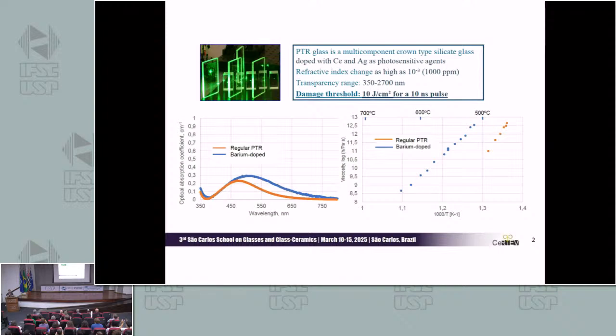First is irradiation, at which step the silver ions get an electron. At the second stage, it's a heat treatment. The silver atoms aggregate into nanocrystals, and at the third stage, at the heat treatment, the sodium fluoride aggregates on the silver nanoparticles.